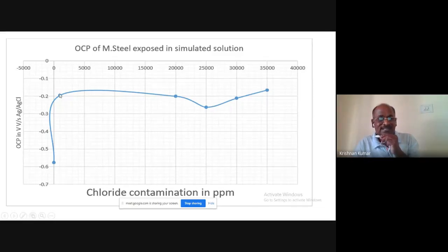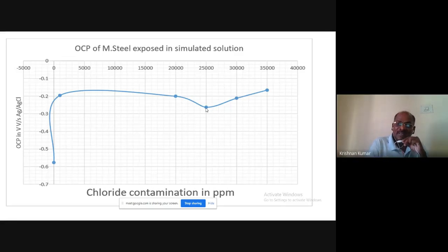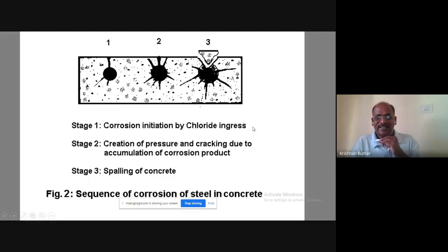That means less negative. And further adding chloride, it goes on, and after that it is decreasing. Why is this decreasing? Because the 25,000 ppm of chloride has already started corroding. The corrosion product formation creates further resistance. Because of that, the conductivity reduces, and correspondingly the open circuit potential increases in the negative direction. So this is the understanding of this project.